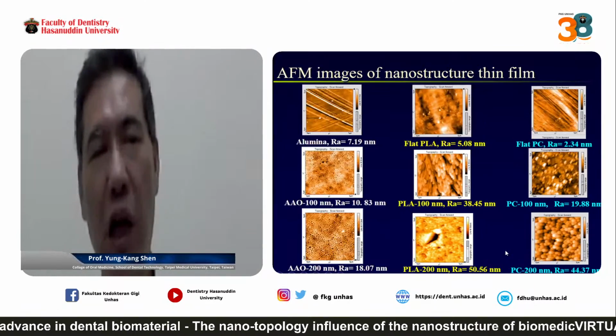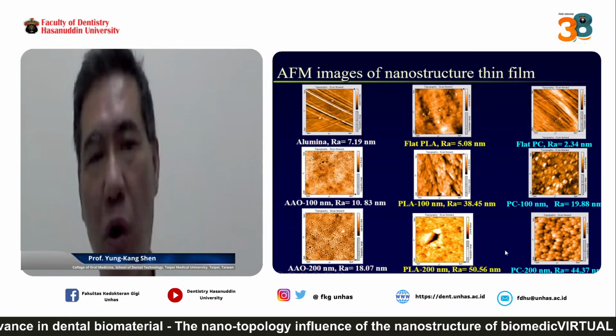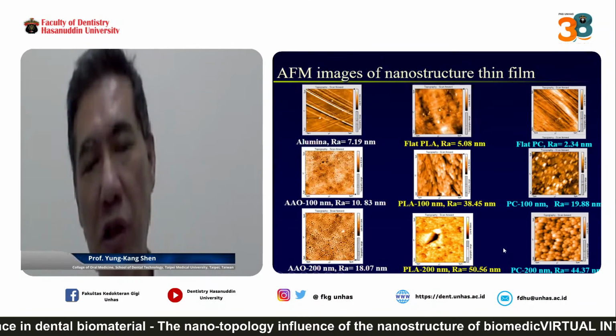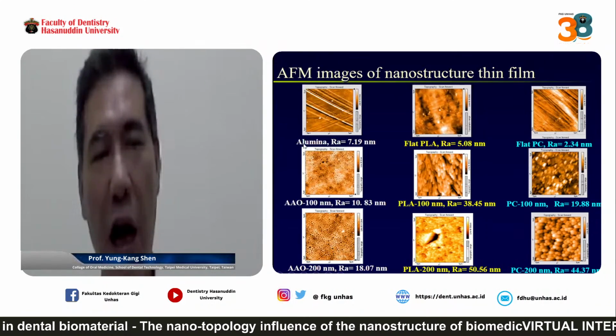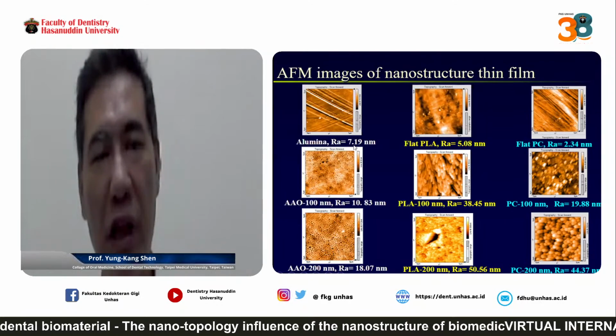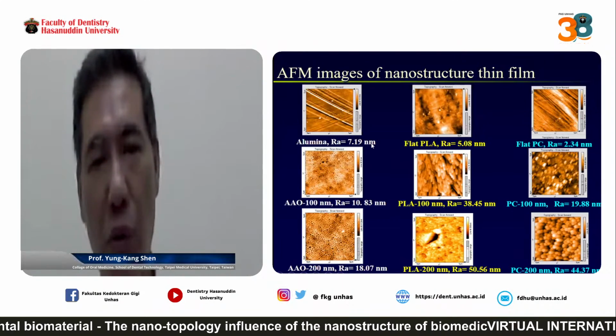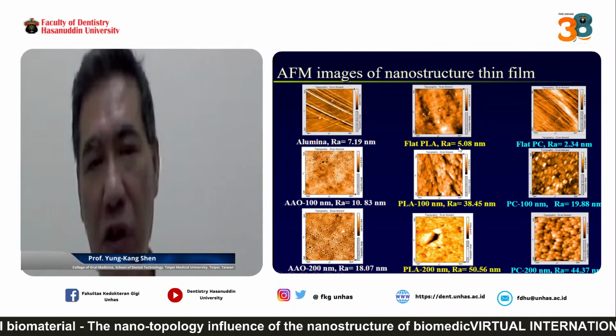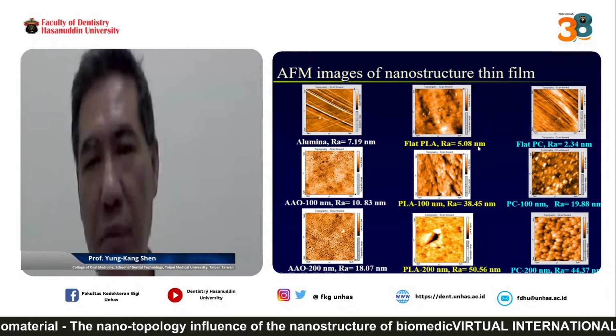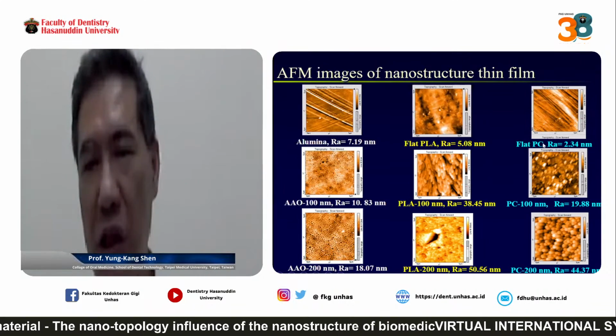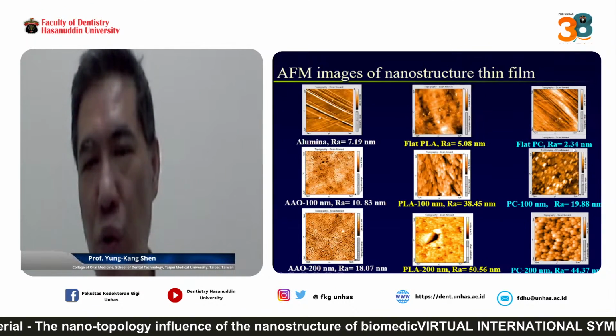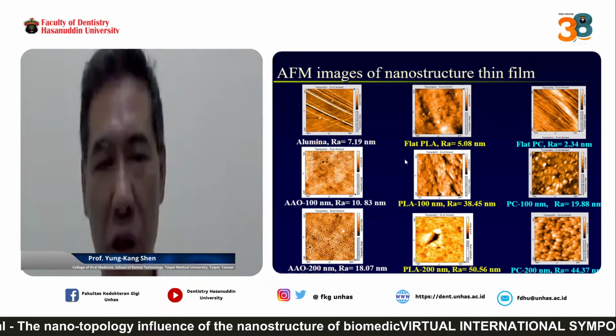Now I will show you the AFM image of the nanostructure of the thin film. The image shows the surface roughness. You can see the alumina AAO roughness is 7.19 nanometer. Flat PLA surface roughness is 5.08 nanometer. Flat PC surface roughness is 2.34 nanometer.